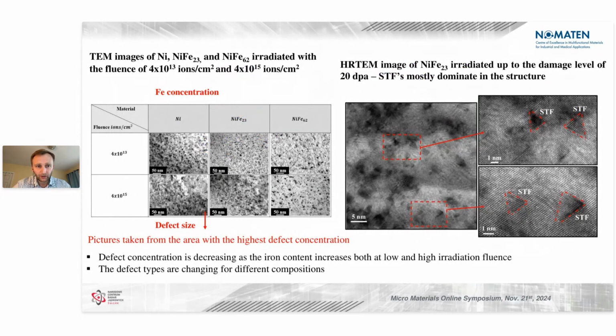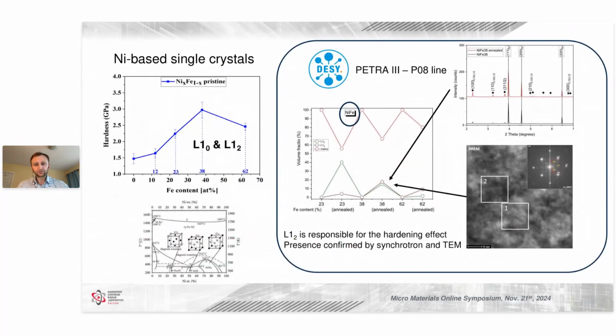As I said, this was confirmed by transmission electron microscopy and allowed us to understand what is happening within the nickel-iron system. Ion irradiation is one part of the story. Another part of the story, when one deals with nuclear energy, is temperature. We basically annealed the same alloys, and we saw that only the effect of the temperature results in hardening measured by nanoindentation.